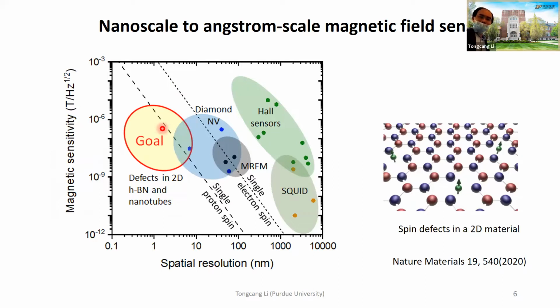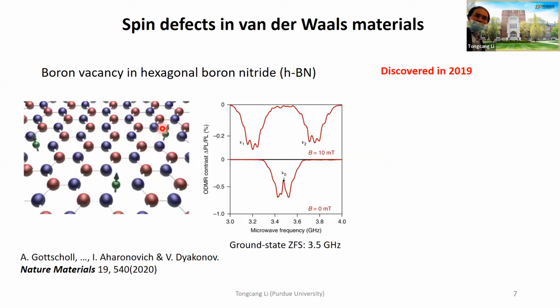Okay. So there is a lot of interest, and people have been searching for spin qubits in 2D material for a long time. It was eventually discovered in 2019. It turned out that the boron vacancy in hexagonal boron nitride is a spin 1 system. And not only spin 1, it's also an optically addressable spin 1 system, which means it is similar to diamond NV. You can use a laser beam to polarize it and then read out the spin state. Boron vacancy is basically a missing boron atom in the lattice, and an electron can be trapped in the vacancy.